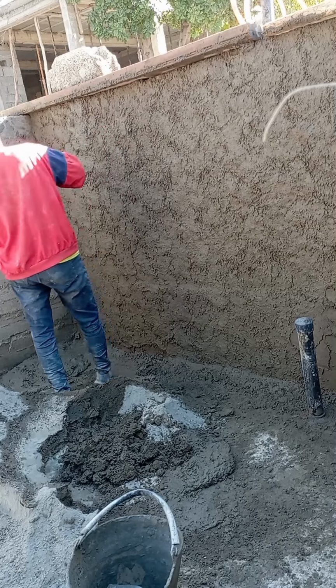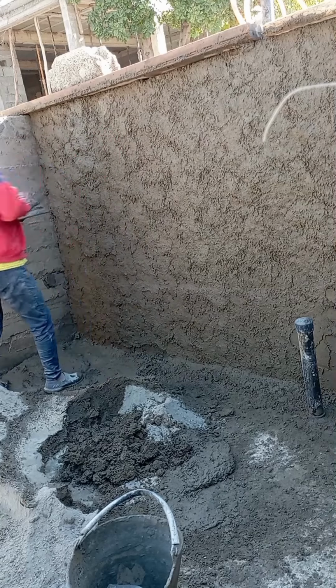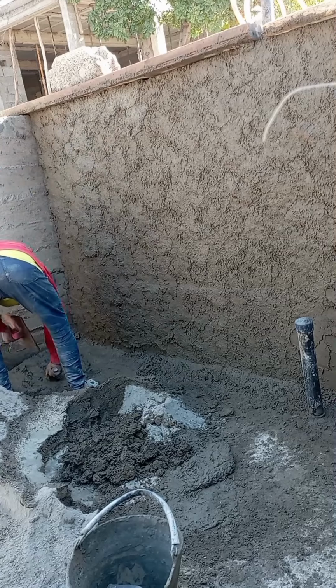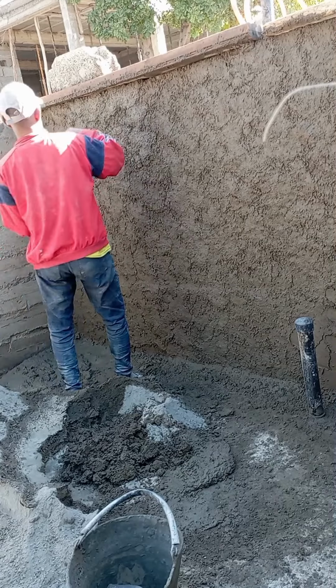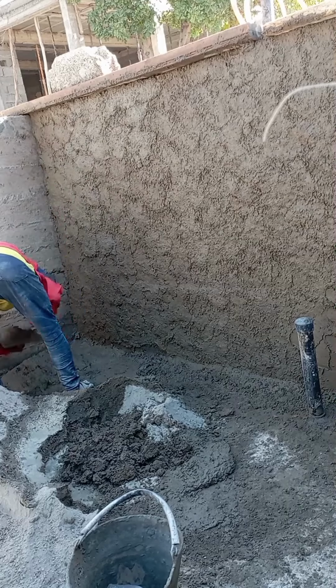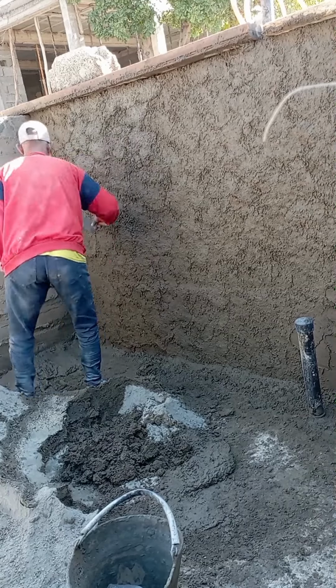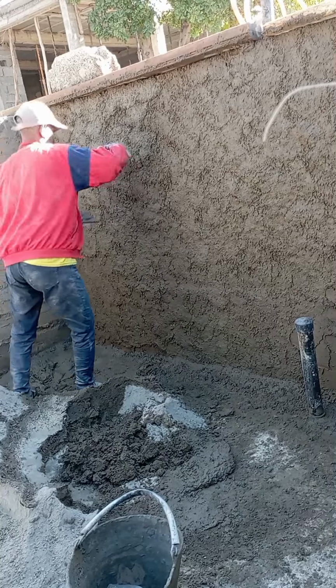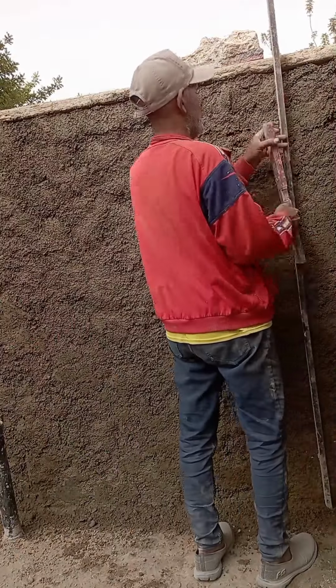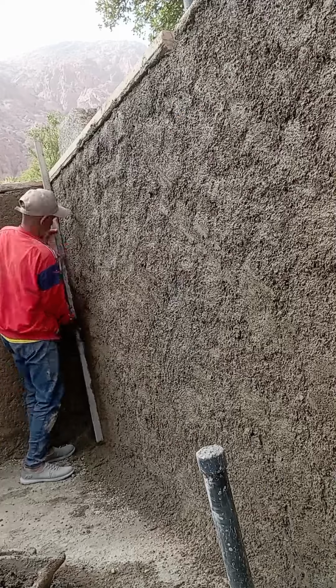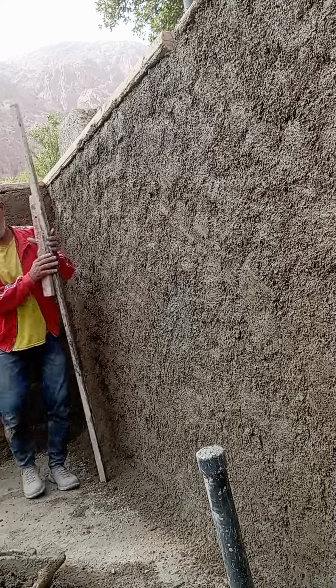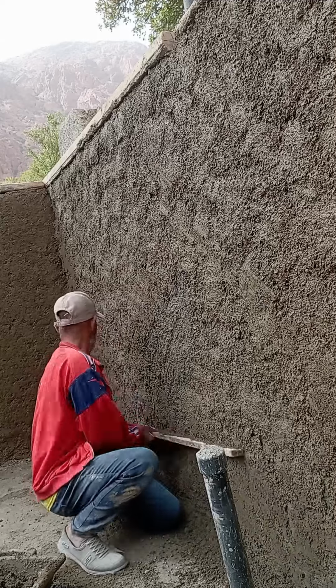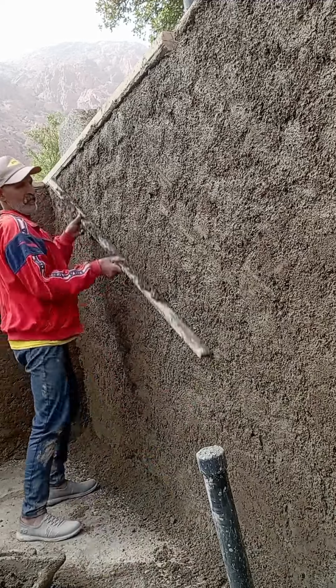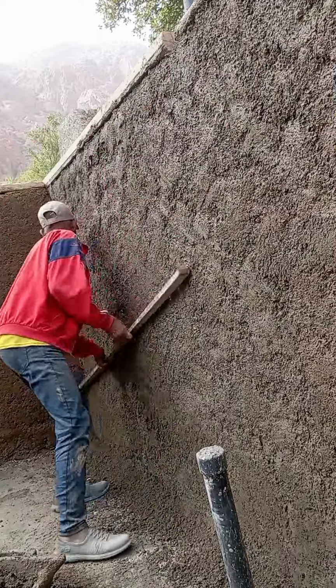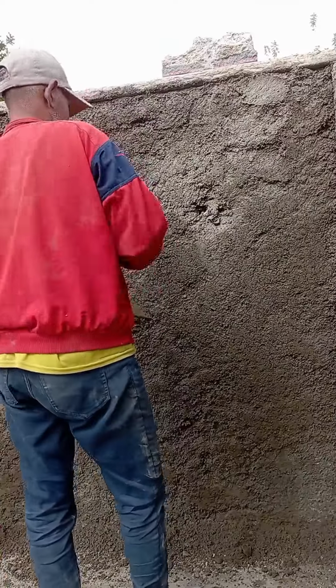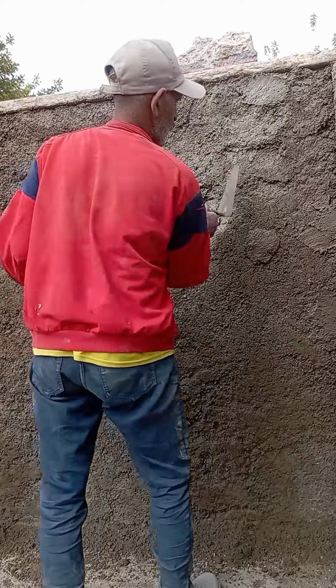Common mistakes to avoid: poor surface prep. Plaster won't adhere properly to dusty or greasy surfaces. Too much water. Overwatering weakens the mix and can cause shrinkage cracks. Plastering on dry walls. Always dampen the wall before applying the mix to avoid water being sucked too quickly from the plaster. Delaying the second coat too long. If you wait too long between coats, they won't bond properly. Skipping curing. This is the number one cause of premature plaster failure.